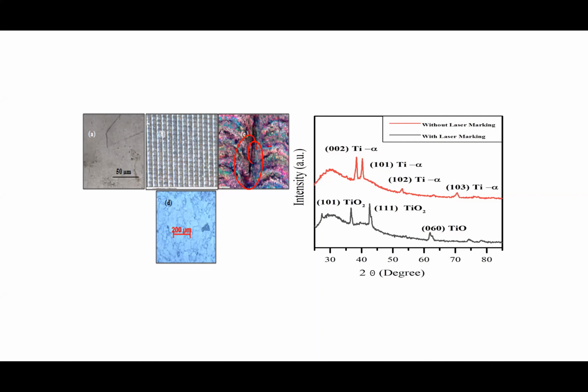And the temperature in the irradiated region of the sample rises, which enhances the diffusion of nitrogen into the surface and decreases the beta titanium content due to the laser surface melting, which is attributed to the stabilization of the martensite phase. Okay, so after a laser treatment, that is the reason we have some kind of structures coming out of it.